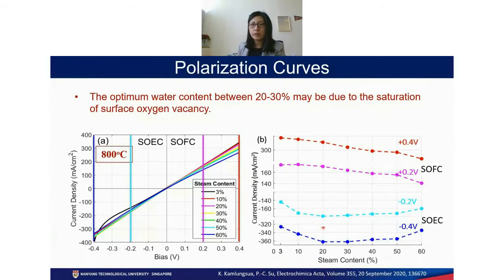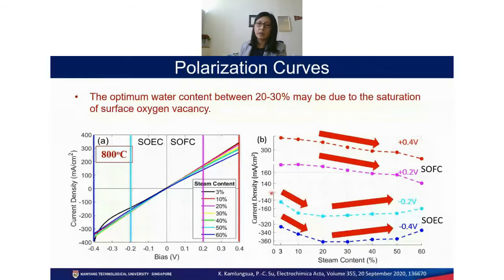Okay, so again, for SOFC, as the steam content increases, the current density drops gradually. So again, this proves that it indeed has something to do with the dilution of the hydrogen content by the steam. And for SOEC, it also follows the same trend as our DRT and EIS result: the current density drops with the increase in moisture content, stabilizes, and then slightly increases. Okay, so this is the polarization curves. So it's this kind of optimized current density for SOEC, again around 20 to 30%.